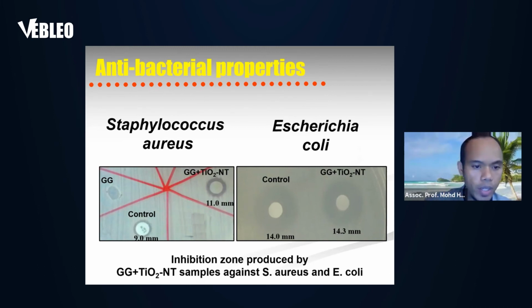Here we can see some inhibition zone for the control sample, and then again we can see the inhibition zone for GG plus titanium dioxide nanotubes biofilms, around 11 millimeters. Unfortunately, for pure GG film, we cannot observe any inhibition zone. Right, the same result goes to